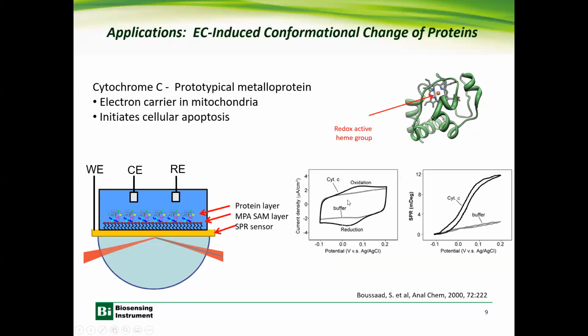And so the cyclic voltammetry on the left figure here, you can compare the one that has a pure buffer. You see the CV shows only a square-like, typical capacitor behavior, which corresponds to the double layer capacitance of the system. And the other one, when you have cytochrome C, you have the oxidation peak and the reduction peak corresponding to the reaction of the heme group, and so indicates the electron transfer during this process. And this oxidation and reduction cause the physical state change, and is measured by the SPR.